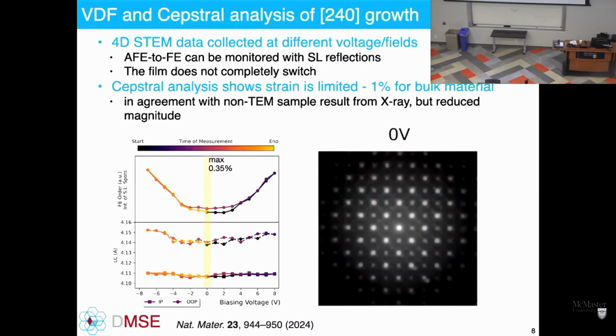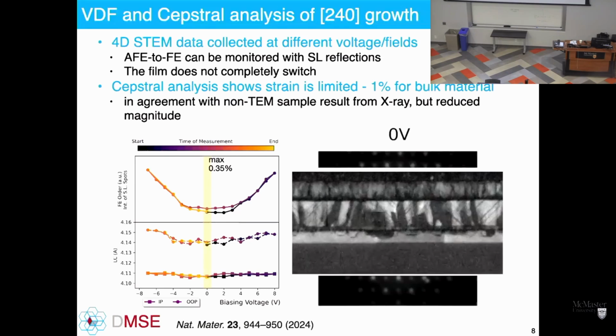So you have strong ferroelectric order to either side. And we see some change in the lattice parameter. That strain, though, is very small. We're not getting a lot of response. But we can choose just one of those reflections in that diffraction pattern and map a two-dimensional distribution of